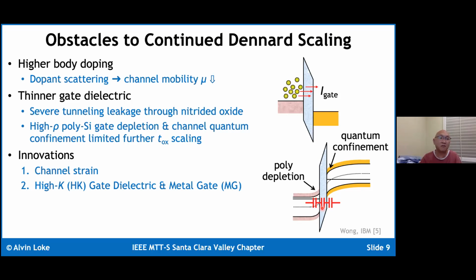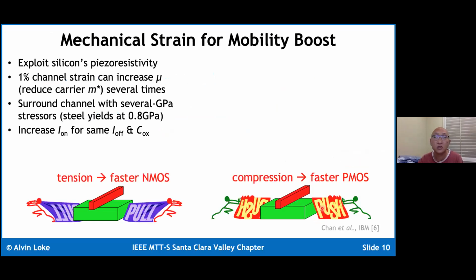Okay, so what have we done to fix that? We have introduced channel strain, as well as high-K, or high permittivity, gate dielectric and metal gate. So what are these? What do these innovations look like? So from a mechanical strain perspective, what we're doing here is we are physically exploiting silicon's piezoresistivity, which means that the electrical properties of silicon depend on its mechanical strain state, whether it's in tension or compression. Okay, so silicon is extremely piezoresistive.